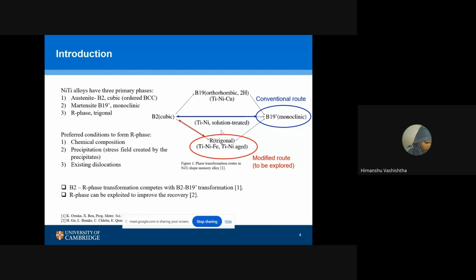And why we are emphasizing this R phase? Because if we are applying, let's say 10% of the total strain, we can form the R phase and return to the original shape. So in this manner, we are not deforming our material too much, but this is limiting our loading application as well. So it's a trade-off between the application of the load and your recoverability or the life of the component.